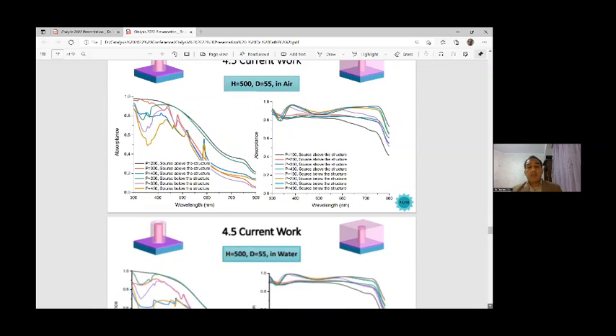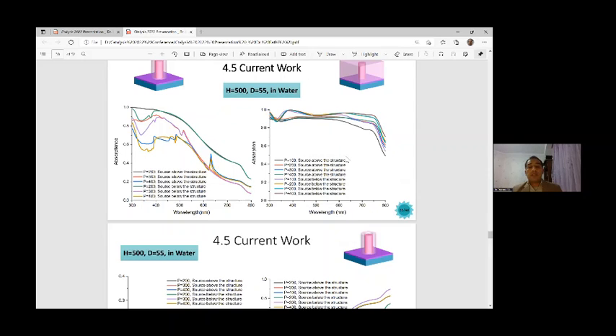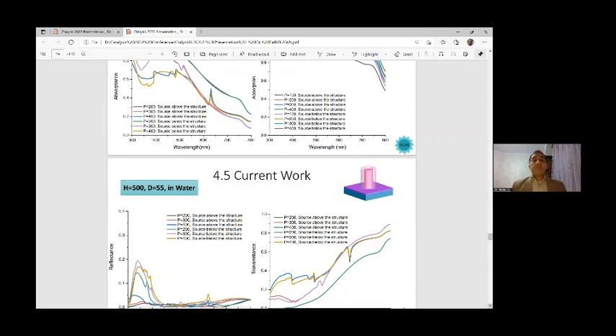Here, for example in slide 35, for a height of 500 nanometers, a nanorod diameter of 55 nanometers and water as the environment, you can see the absorption and absorbance. From the comparison between these curves, we can conclude that the absorption spectrum is better for water in comparison with air as the environment around the TiO2 nanorod. Water is better as the final result for the absorption and consequently the performance of the system.